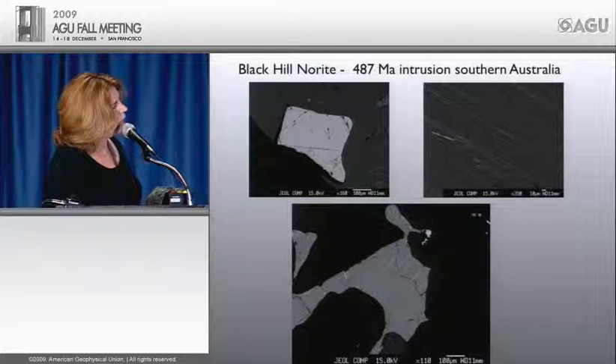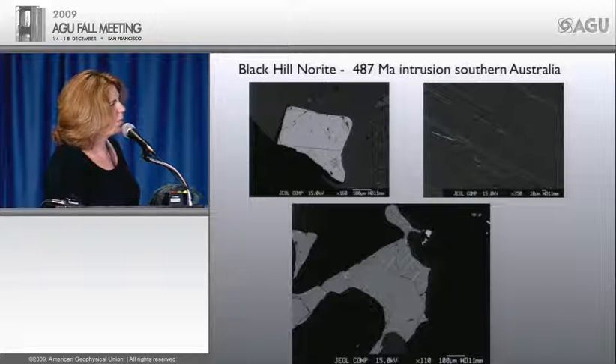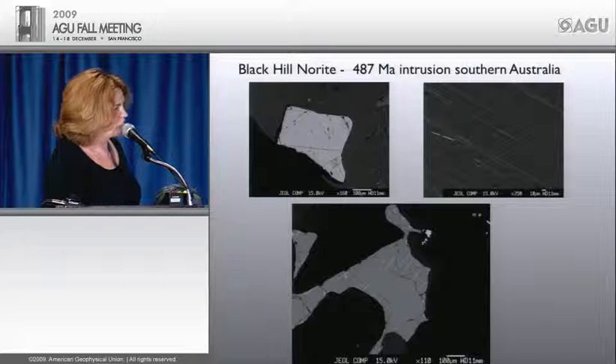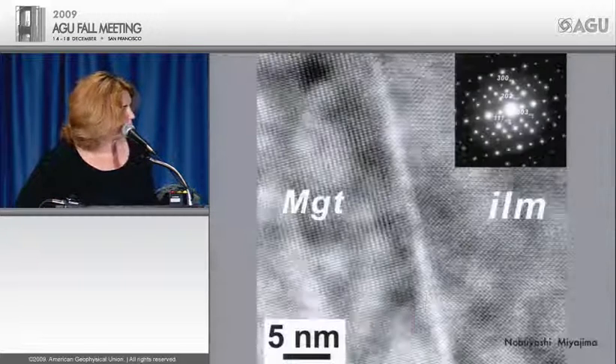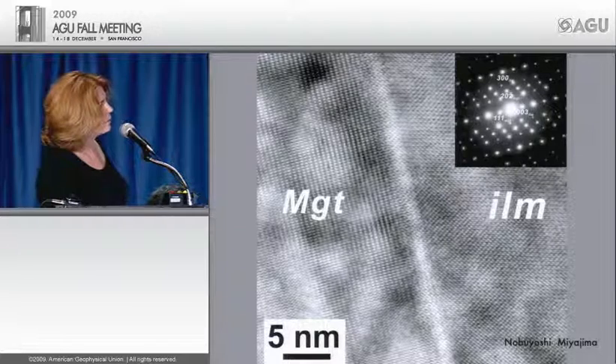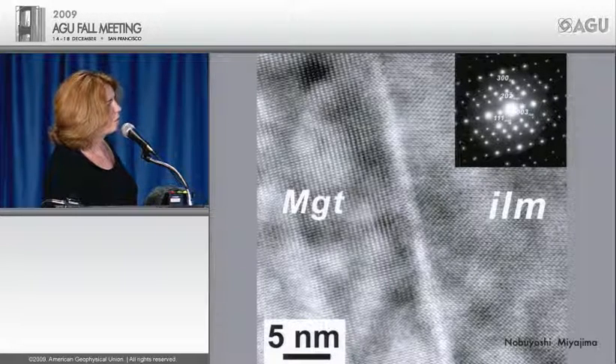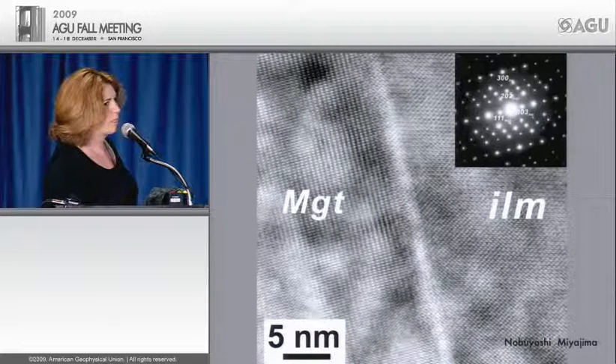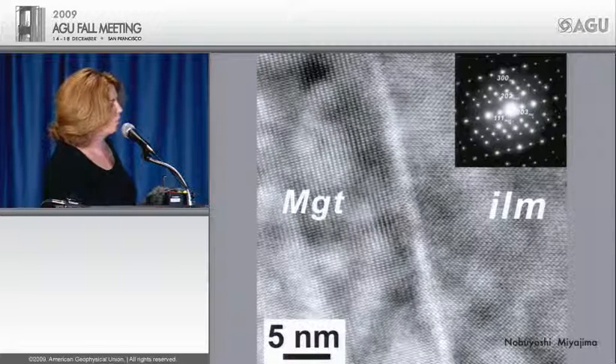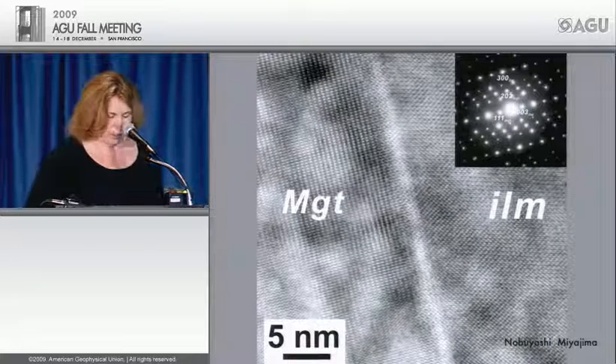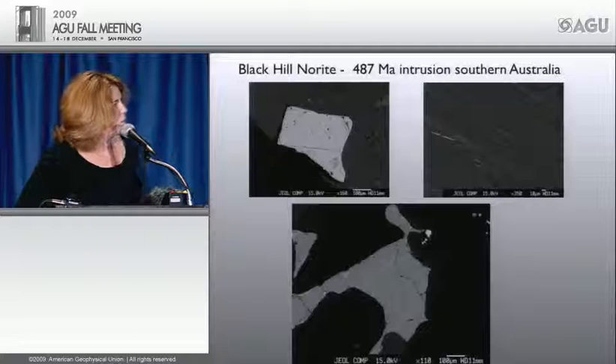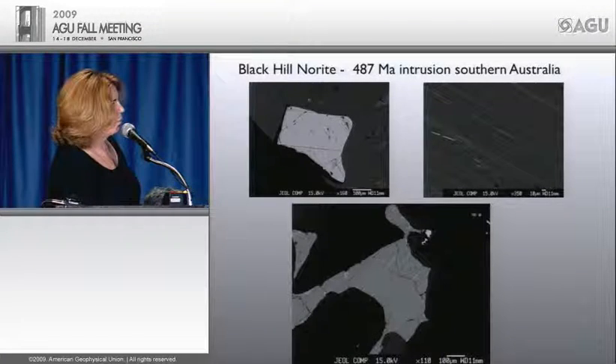And at first I thought we're looking at hematite in here and went to the probe and we didn't get very good hematite numbers and I was bothered with that and we tried it again and we came up with the same numbers. So we went to the TEM. And what we found is here, this is a common zone axis and it's a high resolution image and we're looking at ilmenite, the host is ilmenite. Those lamellae are hematite. They had very odd terminations to them. I mean, they're magnetite. So this is a very beautiful example where we have ilmenite exsolving magnetite.